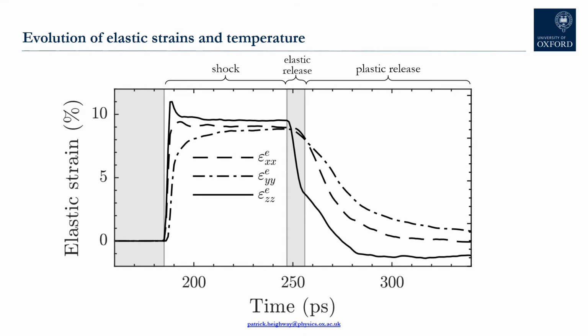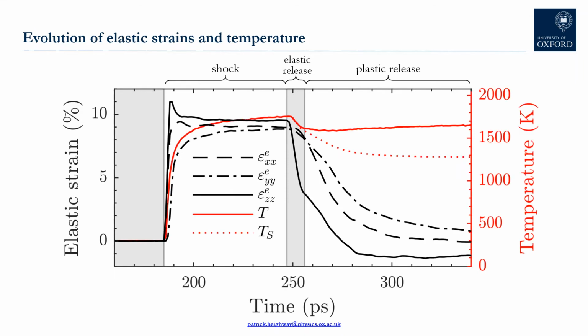If we now overlay the element's temperature evolution, shown by the solid red line, we can see some interesting behaviour. The shock wave first raises the temperature of the crystal from 300 Kelvin to around 1750 Kelvin. Then, during the elastic release phase, the crystal starts to cool, which is expected because of the thermoelastic effect. However, as soon as plastic flow begins, the temperature of the crystal practically stagnates.